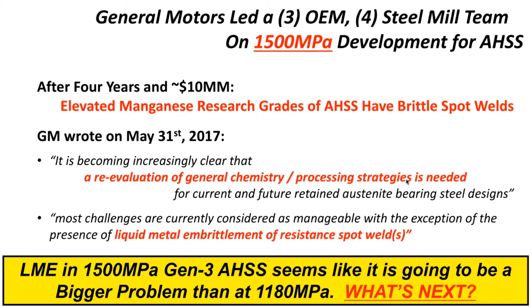So it might be interesting to have 5 or 7% manganese steel at 15% elongation, but if you can't galvanize it and then spot weld it, it's going to be a problem. And right now they do kind of deal with retained austenite in 1180 megapascal steels, but to get to 1500 and the elongation needed, they're going to need more manganese and more susceptibility to liquid metal embrittlement then. If this isn't the solution, what's next?